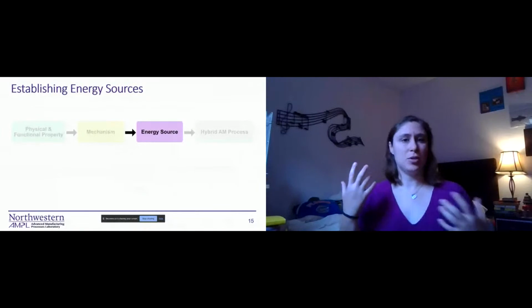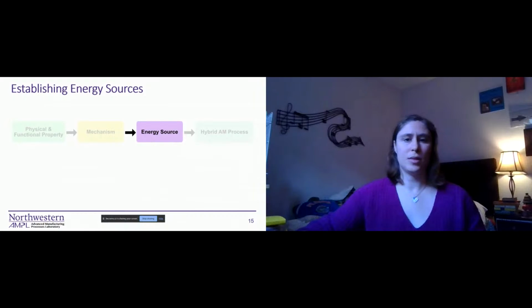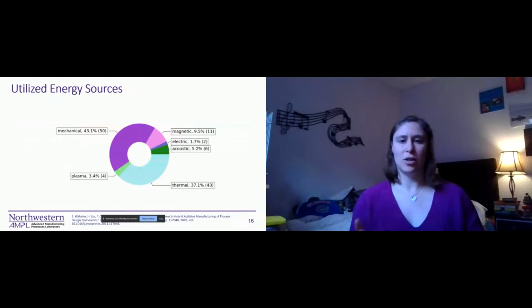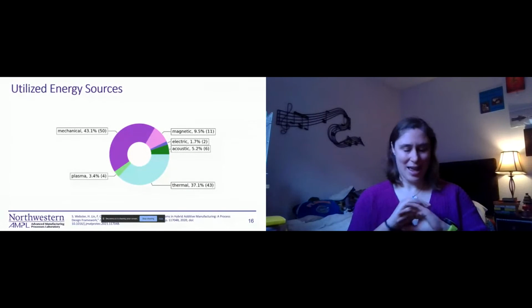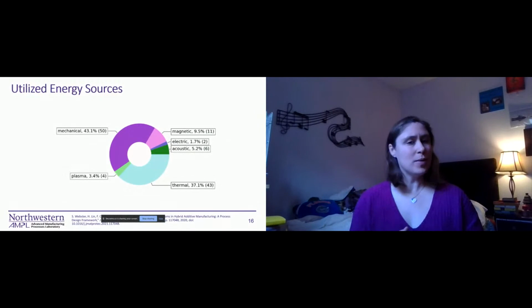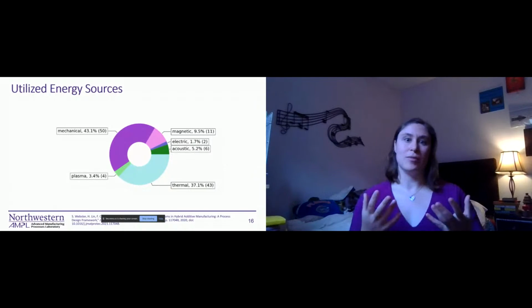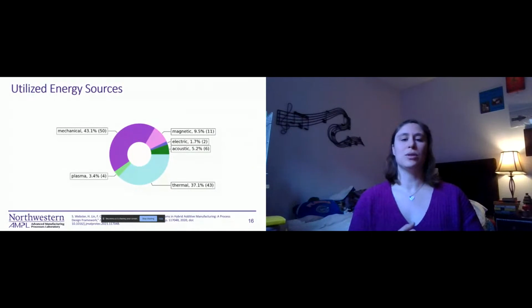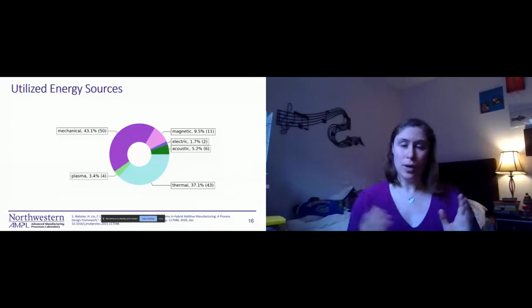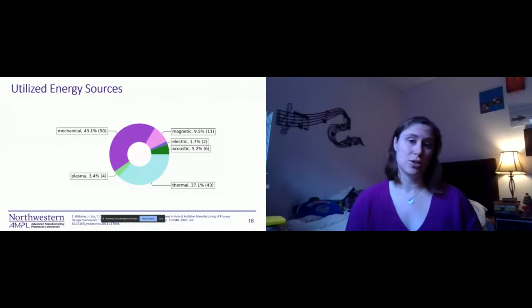So next, looking at the types of energy sources that have been used. We have mechanical, magnetic, electric, acoustic, thermal, and plasma. So it's very evident in this donut chart that mechanical and thermal energies were heavily utilized across the board. They're very easy to implement, and they were very obvious energy sources to use with AM materials. Things that were researched less were obviously magnetic, electric, and acoustic. Magnetic fields can actually be used to change the melt pool flow and velocity. And acoustic energies were commonly used for workpiece vibration in order to release pores, as I had mentioned before.